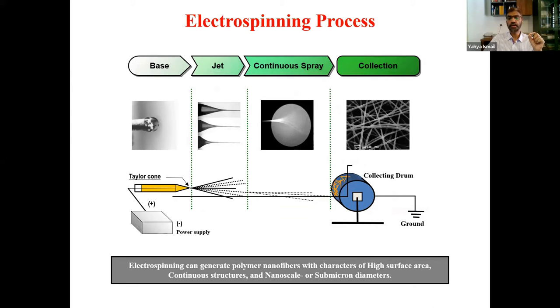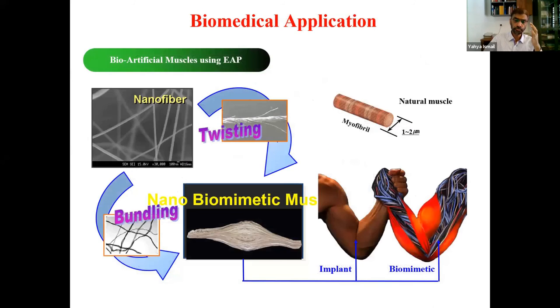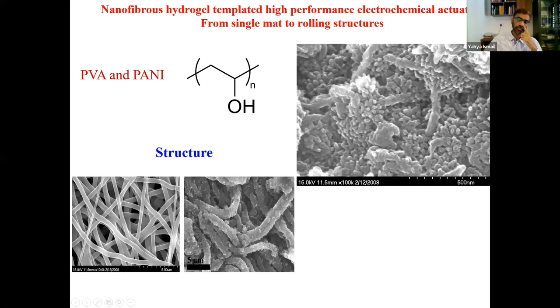And then we hybridized it with conducting polymers. We tried different types of variation, even twisting with nanofibers. And one of the challenges was to improve the strain. So with polyvinyl alcohol, these are the nanofibrous mats we produced and then coated with conducting polyaniline. And then you see, from initially we got 0.4% strain.